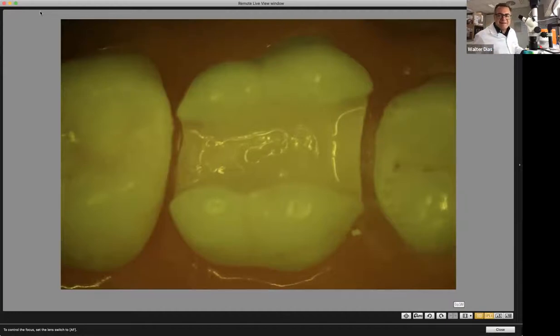And what I see dentists all over the world doing is generally a little more, but that's less than 2 seconds, yeah? And so the adhesive is not gonna cure properly because the solvent is not evaporated. And this is gonna cause a huge problem for the long-term survival rate of this restoration. Right? So again, let me repeat this.